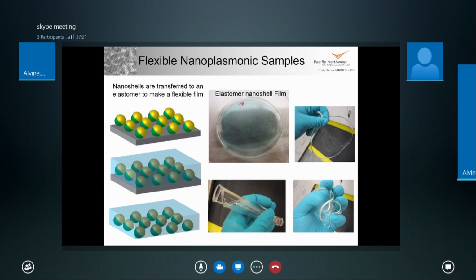These can be made on flexible surfaces. You can either directly deposit them on flexible surfaces, or you can remove them by putting down an elastomer and peeling them off, so you can create something that's very flexible. There's potentially some room in the future for these things to be incorporated into wearables, because the nanoshells are independent, so you don't have an issue of cracking or breaking of the films. So wearables might be something where these things could be very useful.